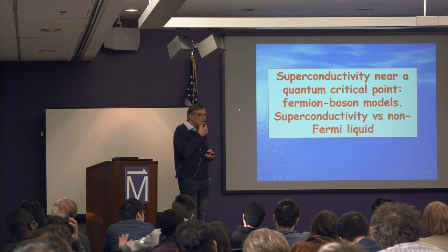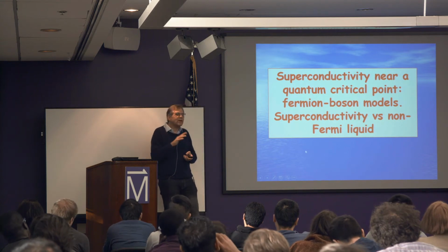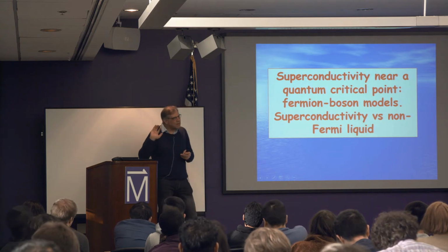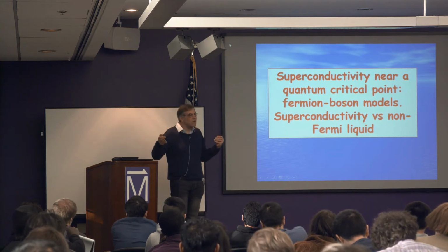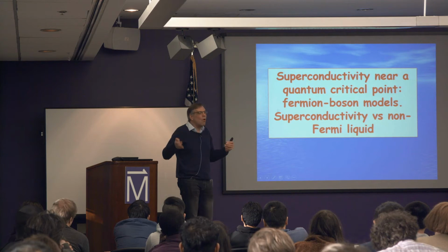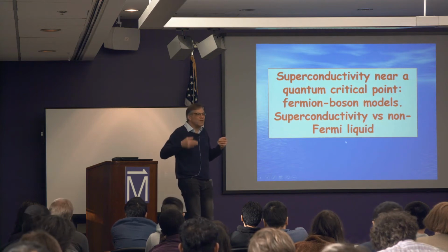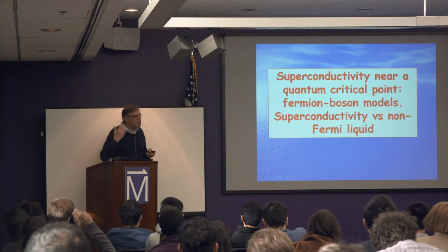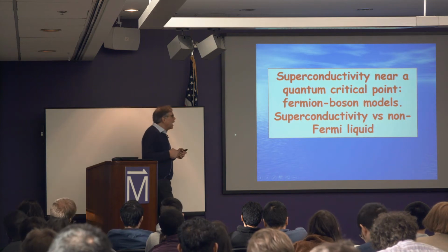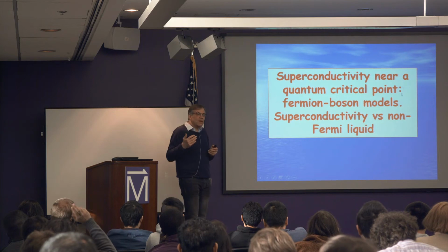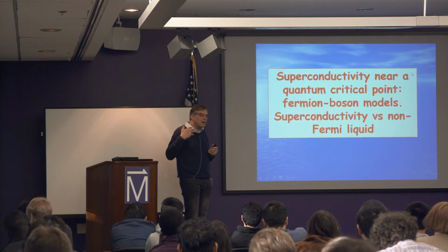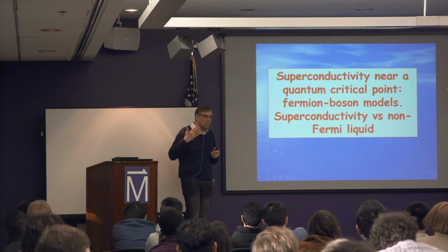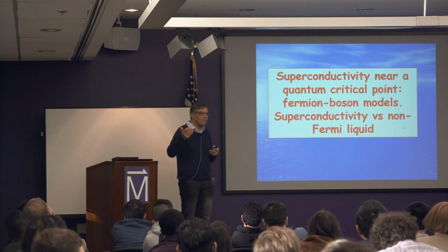What I was trying to say is that the previous approach worked under the assumption that the theory has logarithms. For iron pnictides, yes, that is the case if you separate scales, but for cuprates, generally no. There is no such thing as logarithms in different channels unless you are very close to the one-half point, which not all systems are close to. And then you can ask a different question: how can I think about the system when I cannot do perturbation theory enhanced by logarithms?